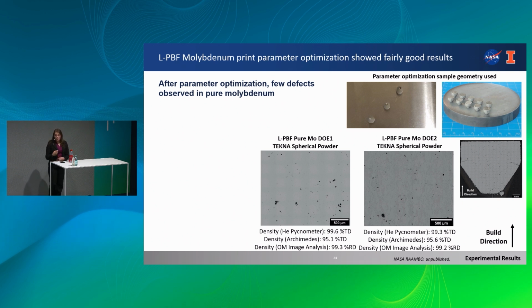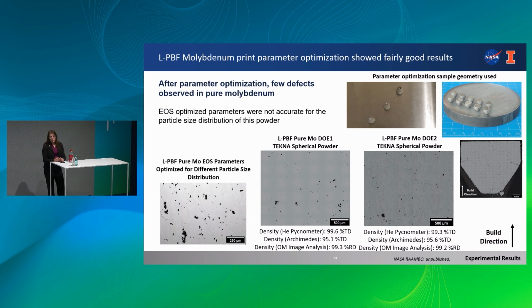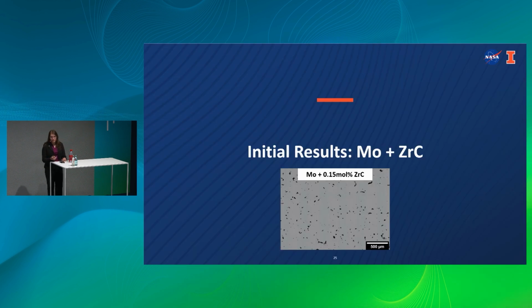From there, we did a bit of print parameter optimization on the pure molybdenum using these kinds of specimens, and this helps with rapid development. As you can see, once we did this print parameter optimization, we got pretty good results for the pure molybdenum. We previously worked with EOS under a cooperative agreement, and they helped us develop good print parameters for molybdenum, but they had a different particle size distribution. So when we tried to use their parameters, we got pretty poor results, but it gave us a good starting point for our parameter development.